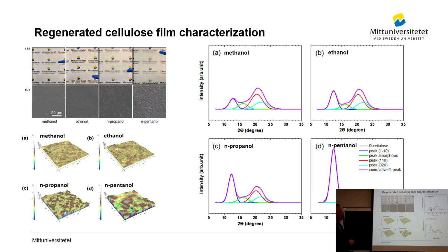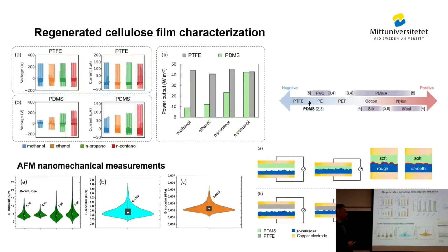And a more important thing, I would say, if you check this plane in the XRD, you can see the hydrophilic plane of cellulose is changing in the XRD when you go to the alcohol. And that also tells you that you change something, which is a very interesting possibility. So we went further and investigated that in this series. And then we used two different counter layers, PTFE and PDMS, towards the cellulose. And we measured how it looked.